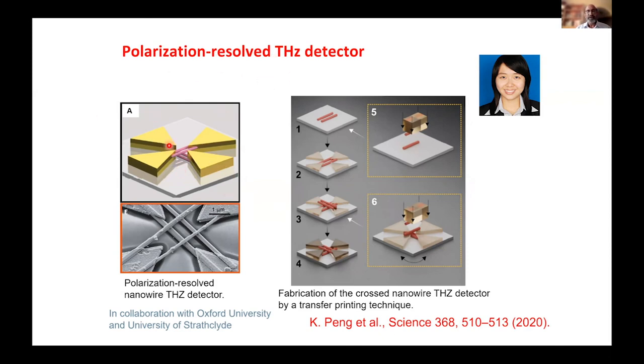You can make these detectors with the so-called bow-tie antennas I've shown you, and then the challenge is to put another detector at 90 degrees to the top one, the bottom one, for example. The challenge is to avoid contact between the top nanowires and the bottom nanowires. That's where she spent a lot of time, along with my University of Strathclyde colleagues. Using the transfer printing technique, we were able to demonstrate this.